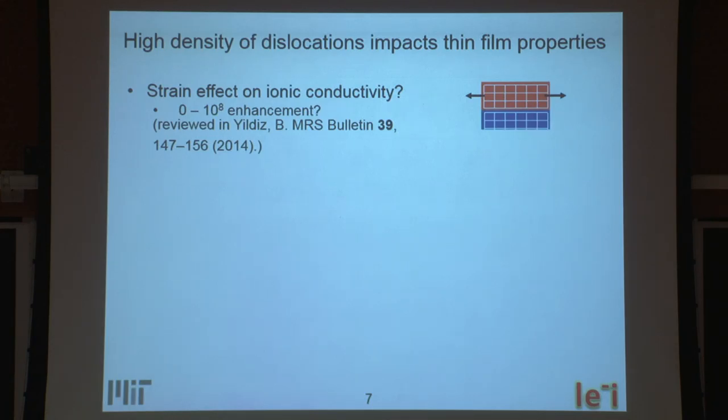So strain engineering means you can do a thin film sample. The blue one is the substrate. They have a certain lattice parameter. And you grow the other type of material on top of the substrate, the orange one. These two materials originally have different lattice parameters. But because we grow one on top of the other, you can manage to change the lattice parameter of the orange one, and therefore you can stretch or compress the thin film. By straining this sample, you can change the E, the reaction barrier, for the ionic conductivity. And therefore, you can enhance it and keep the efficiency of SOFC.